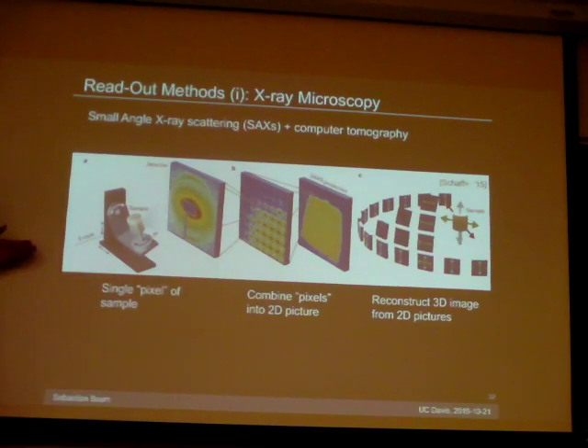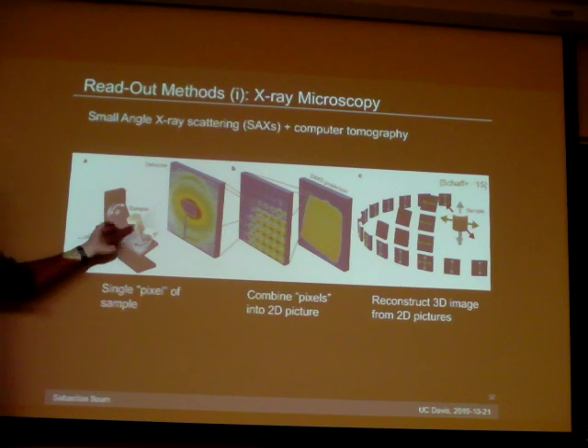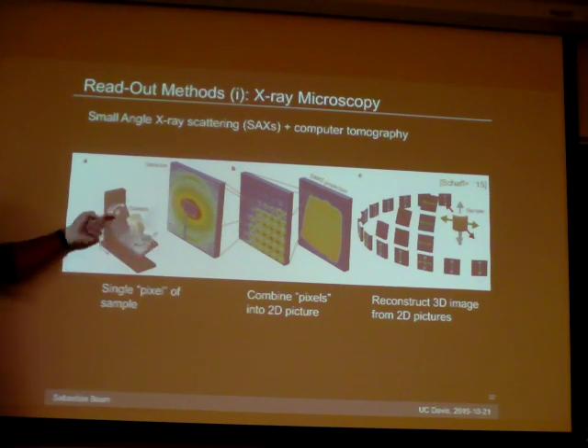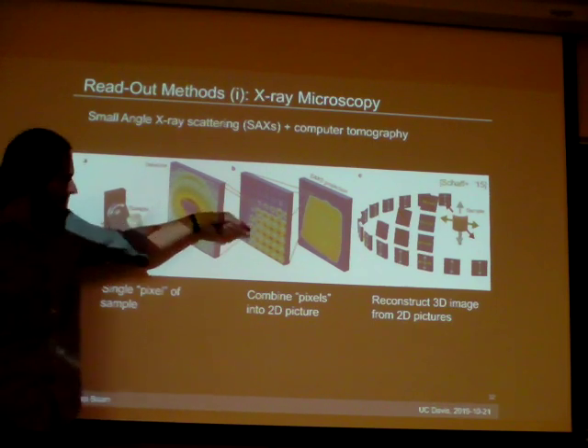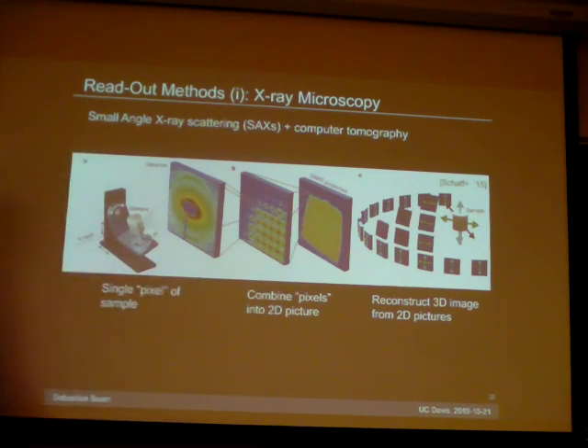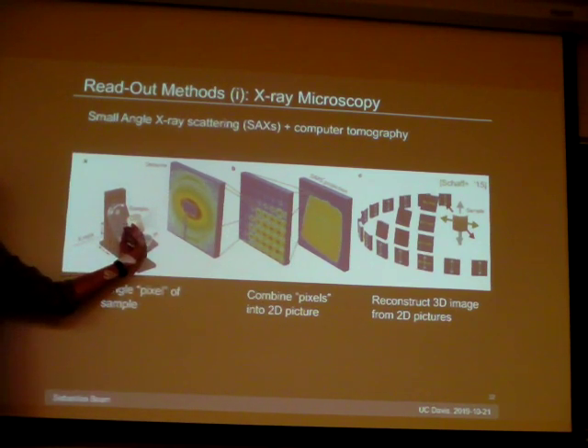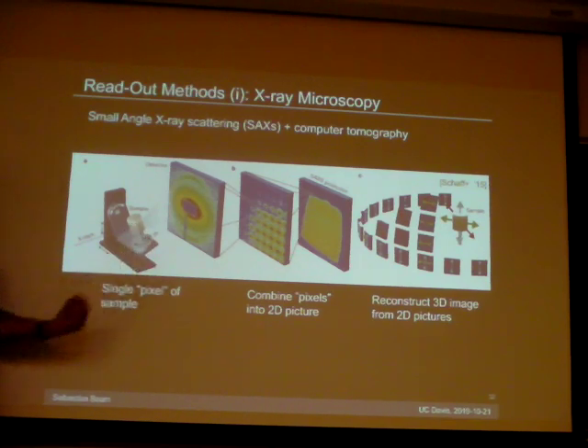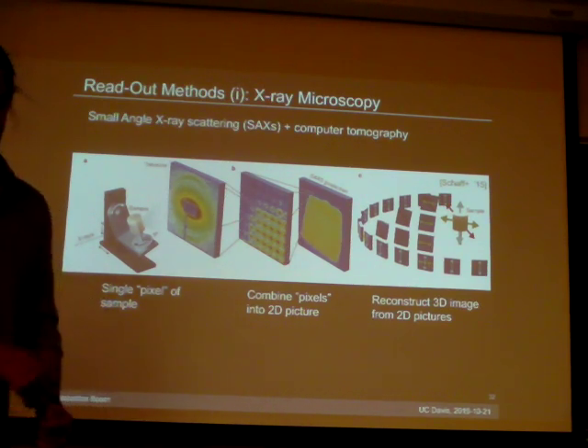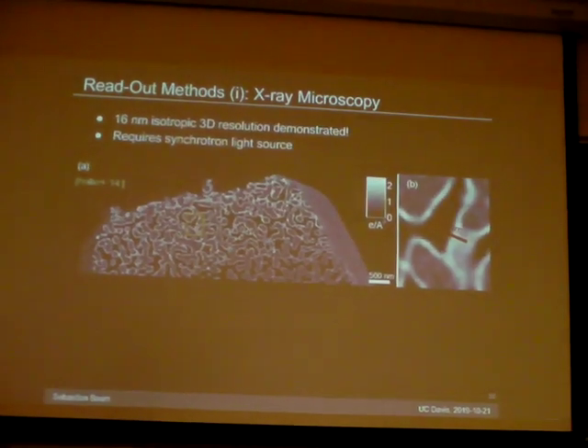So what you do is you take an X-ray beam from a synchrotron, you focus it on your sample, you take a diffraction image, then you scan it over your sample, and you piece together all of these diffraction images. And then you do the same thing you do in a hospital. If you get a CT, you rotate your sample a little bit, you play the game over again, and what that allows you to do is to get a 3D readout of your material, right? You can take a bulk sample and get a 3-dimensional readout of the structure of the material.